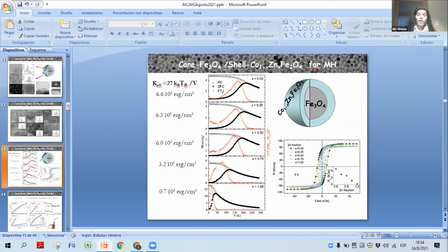Yes. Well, for this kind of measurement, of course, the magnetic field that you apply should be as low as you can. If we reduce it more, we won't observe any signal. So we used to measure with 50 oersteds. If we increase the field, what would happen is the blocking temperature will shift, and as you say, the measurement of the anisotropy constant will be farther from the real one. With this magnetic field, the 50 oersteds,